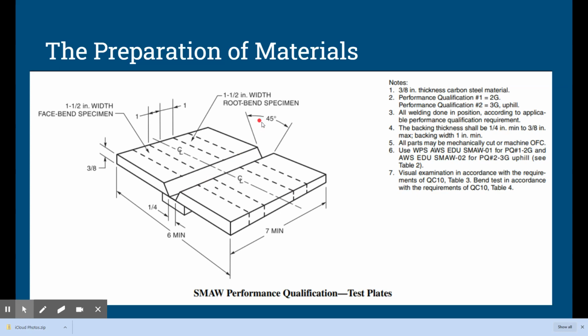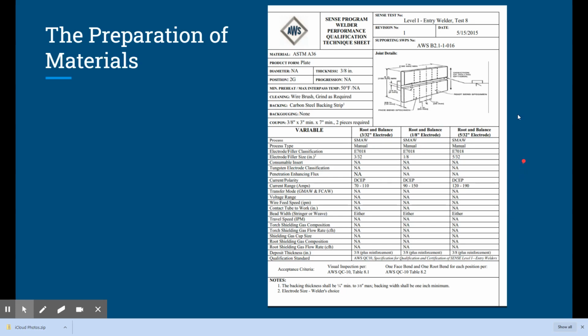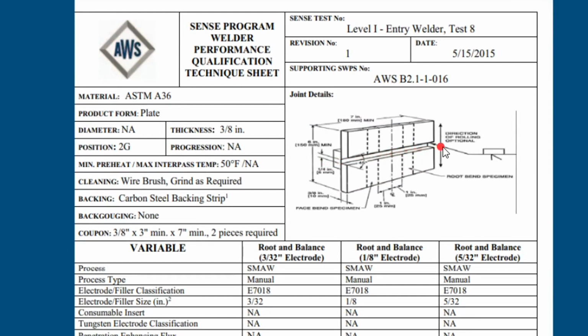Ultimately, that means that we're going to have a 45-degree angle on one side, whereas with a V groove, we're going to get a 22.5 and a 22.5, and they're going to add up to 45. But that's a very common joint fit up for a 2G. I'll show you that on the next page here. So you can kind of see the fit up on a horizontal weld. We're welding horizontal across the joint. The plate is held up vertical. And there's our welding symbol depicting a single bevel with a backing strip on there. So you can see the bottom piece is not beveled at all, but the top piece is. So that's kind of the setup for 2G.